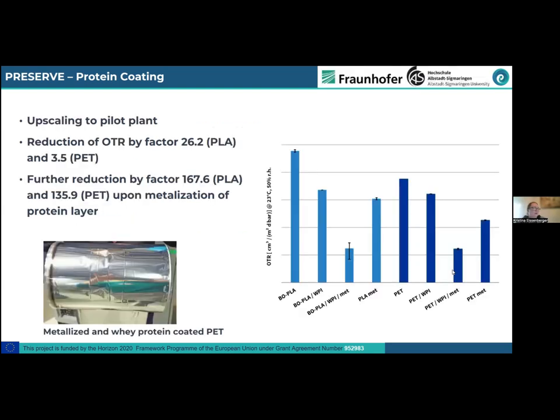Within Preserve, we upscaled it to the pilot plant level, and for PLA, we got a reduction of the oxygen transmission rate by a factor of 26. For PET, a factor of 3.5. And our colleagues from Fraunhofer IVV were even able to metallize this protein layer. That led to a further reduction by a factor of more than 160 for PLA and a factor of 135 for PET.